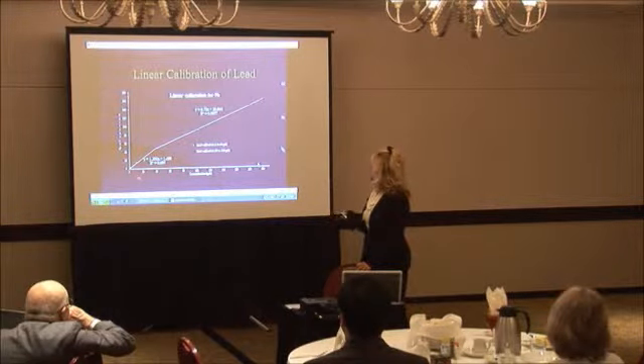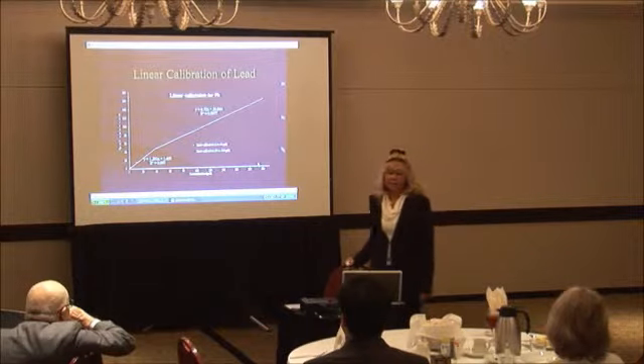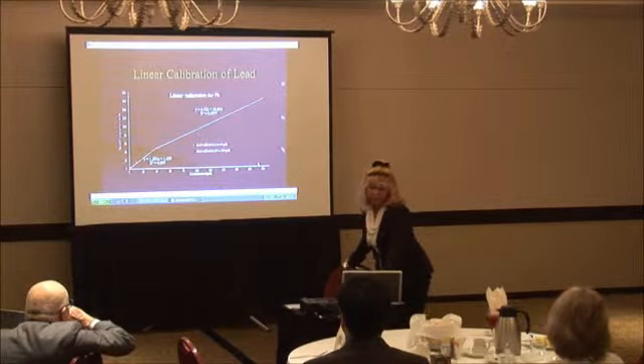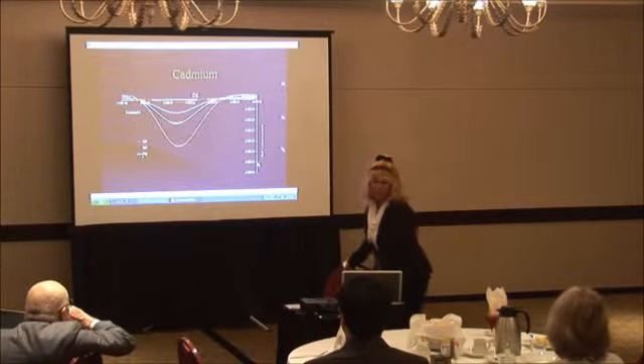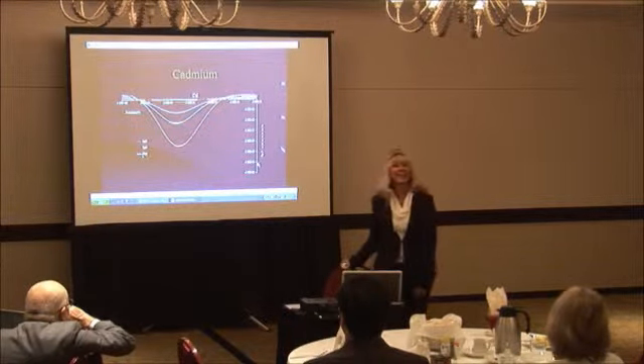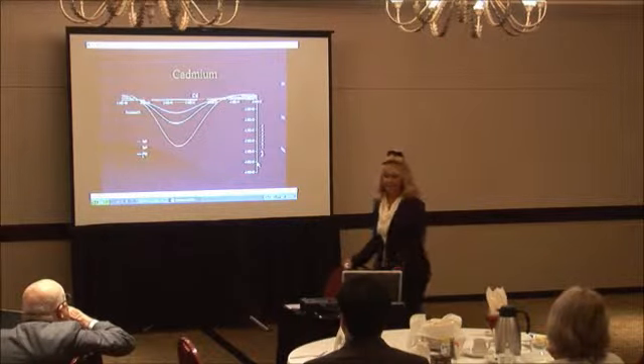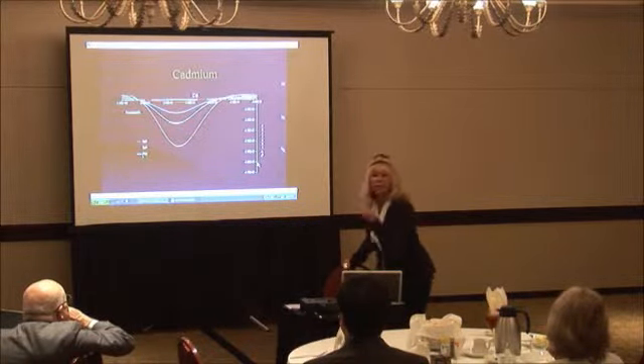So they have plotted current versus concentration, a linear calibration. And obviously what's interesting is the concentrations down here, it's not perfectly linear to the next, but again, this is undergrad research, so we don't yell at them. And this is cadmium. So you can see cadmium, the same concept. You see your peaks. You only get 1 peak for cadmium.